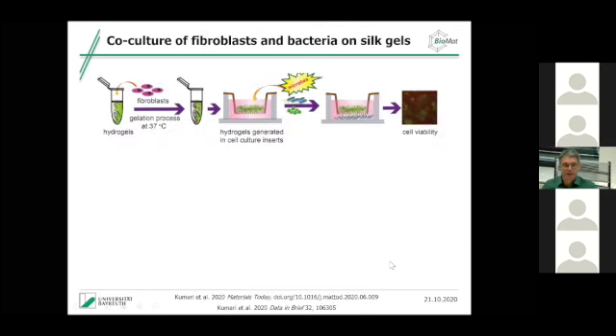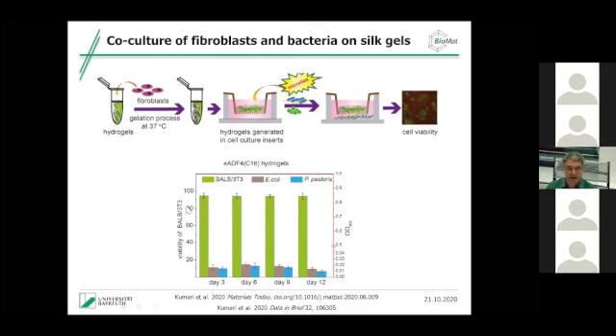So what does that mean? Well, this means now we could do co-culture experiments. So we could actually put fibroblasts and bacteria into the scaffold at the same time. Then incubate that, and then actually check what happens to the fibroblasts and what happens to the bacteria. And the experiment is shown here. So the fibroblasts, they survive very nicely. So we have around about 95% survival rate over 2 weeks. So the fibroblasts are fine.